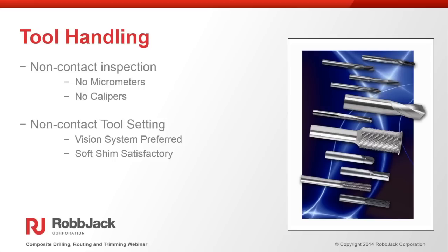On the tool handling side, this is another area where you'll sometimes see failures, or people that said, I've tried PCD or diamond coating and it hasn't worked really well. You really need to address the tool handling. You don't want to use any kind of contact measurement. You do want some kind of vision system. If you do have a probe where you're getting your Z offset on the tool, you can do things as simple as using a plastic shim or even a piece of paper in between the tool and the part, and then just compensate for that.